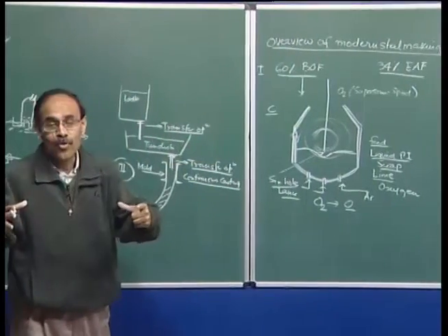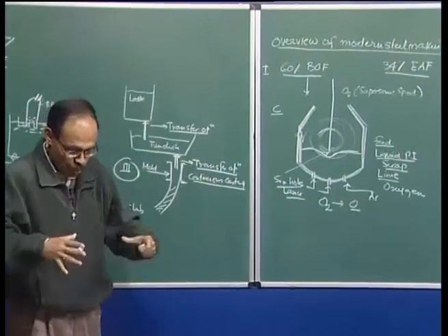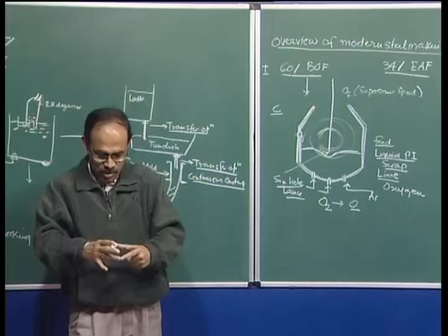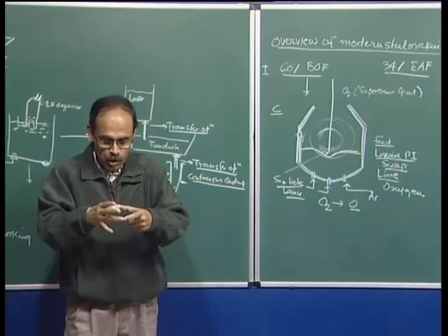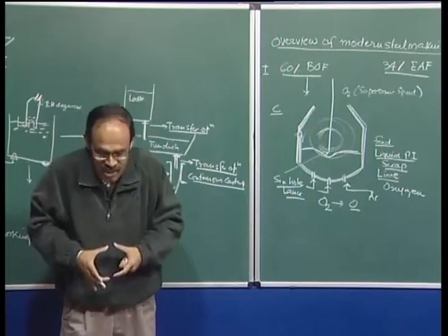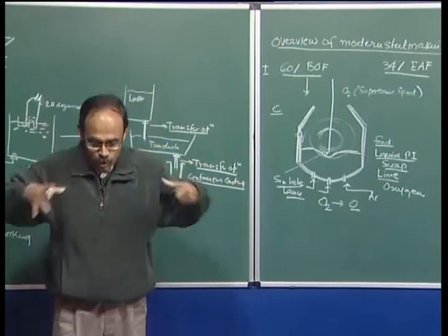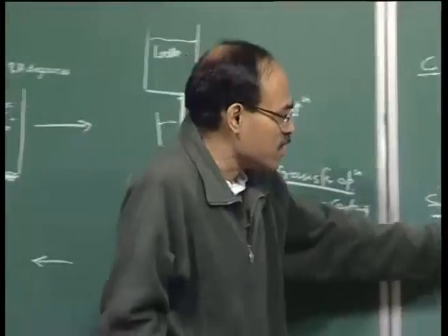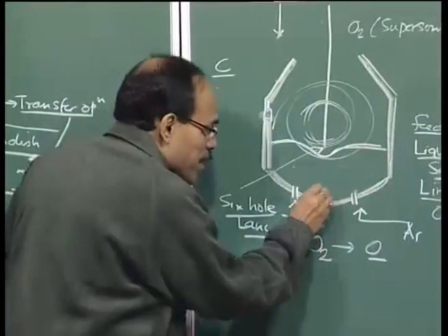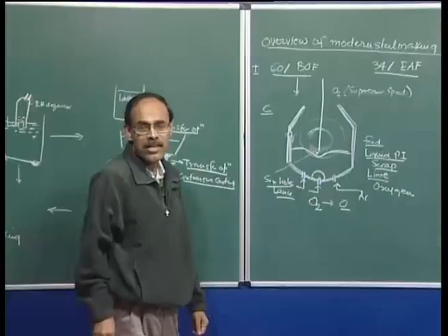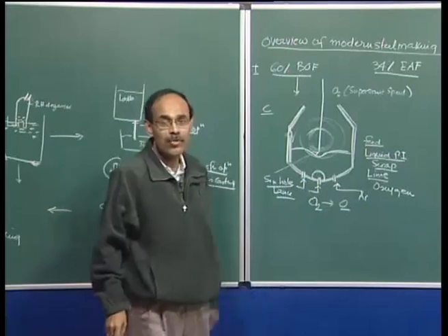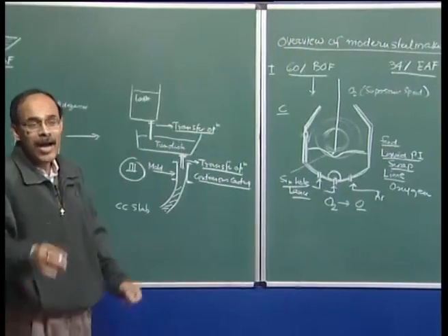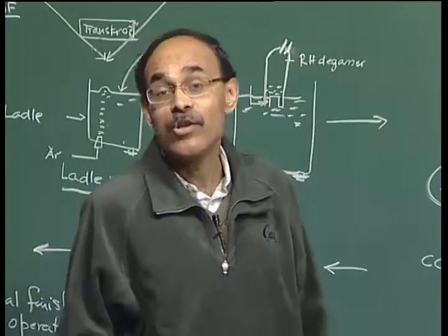And there we use coaxial tuyeres, two hollow cylinders used as tuyeres. So, you have an inner cylinder and then an outer cylinder. Through the inner cylinder oxygen is introduced, through the outer cylinder hydrocarbon is introduced. If oxygen alone is introduced through the tuyere, enormous amount of heat is going to be produced because of the oxidation reaction, and as a result the life of the tuyere can be significantly reduced. So, hydrocarbon serves as a coolant. How? Hydrocarbon cracks, and the cracking is an endothermic reaction.